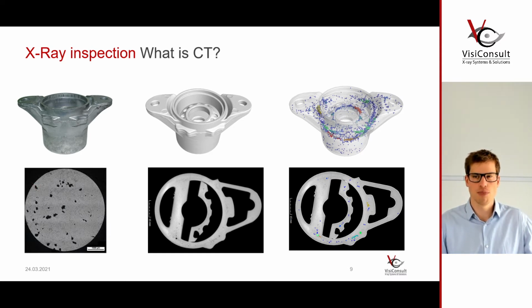So that's why we have computed tomography, which is then providing you a three-dimensional reconstruction of your part, which you could slice into virtual cuts, like a real cut, but just virtual. You generate a digital twin of your part, and then you perform the analysis on this, like you do here. For example, a porosity analysis. You could look for porosity distribution. You could calculate what the implications are for your part if you have such porosities.